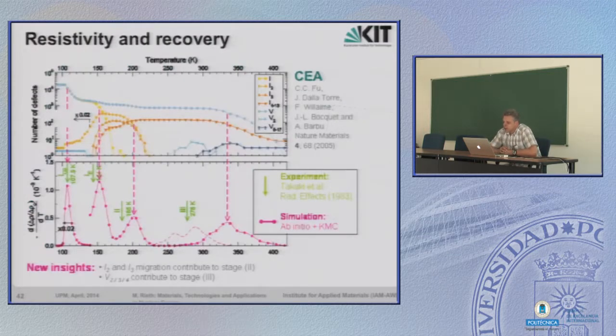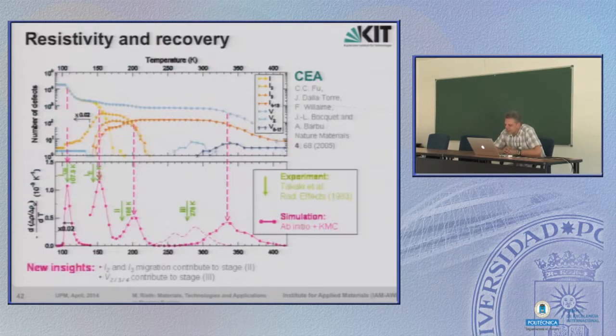There is one type of measurement which you cannot easily recognize on this slide, but we will go through this in a minute. You can imagine that if you have a metal lattice with lots of defects, then it has a consequence on its electrical resistivity. So what one can do in an experiment is measure the electrical resistivity, or conductivity, it doesn't matter, and increase the temperature step by step and see how it recovers. Recovery means that with increasing temperature, there is a chance, and as we will see it really happens, that the defects, or at least some of the defects, vanish. They go away simply by heating up the matter.